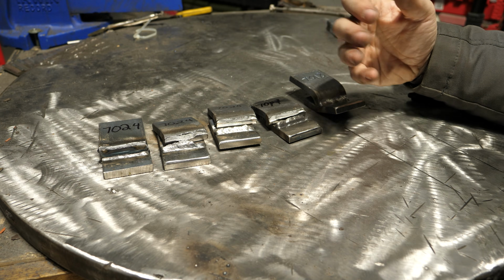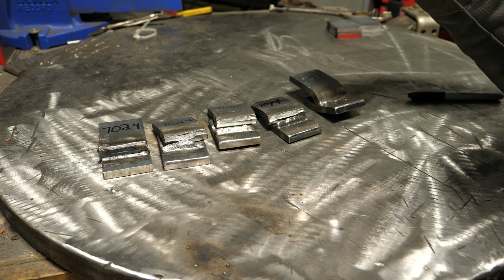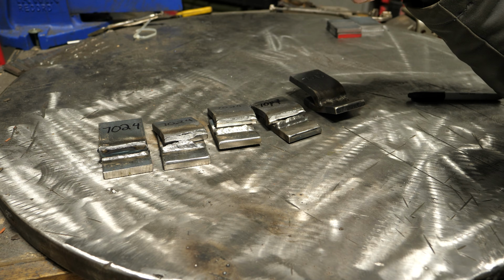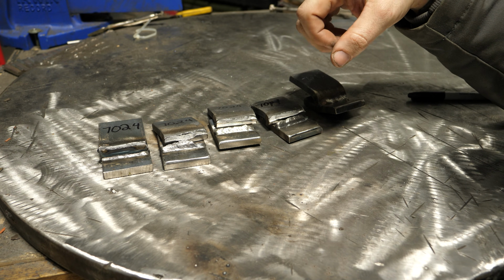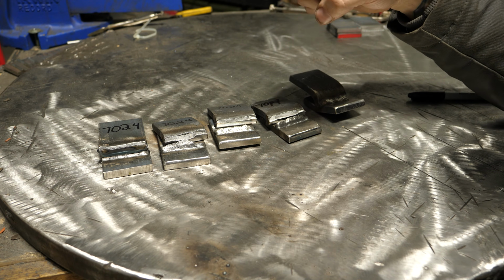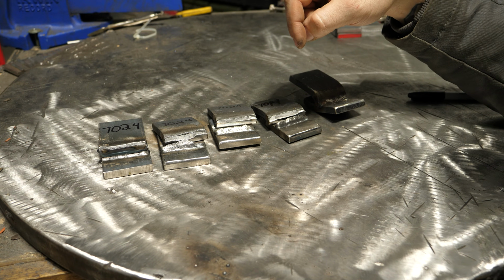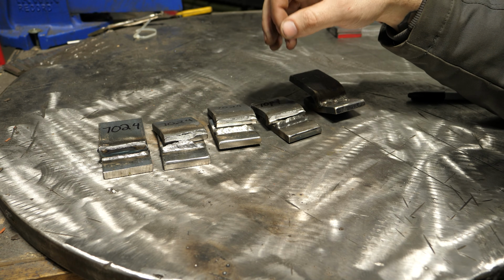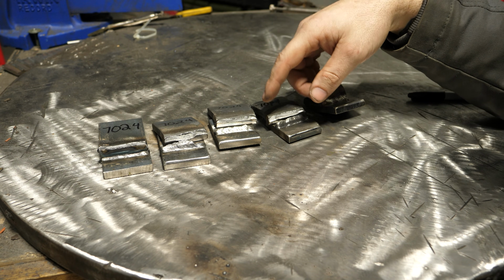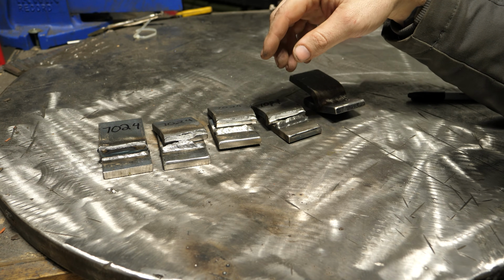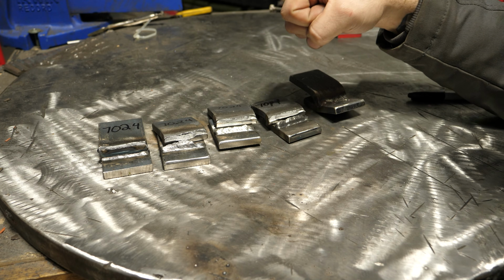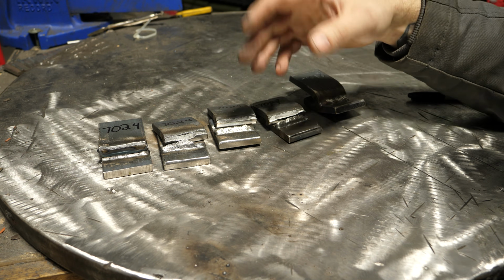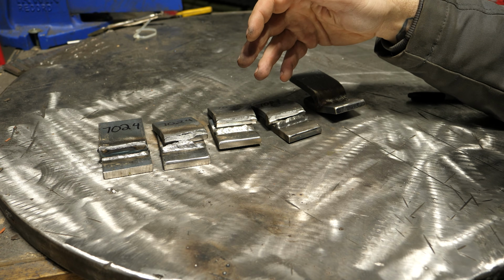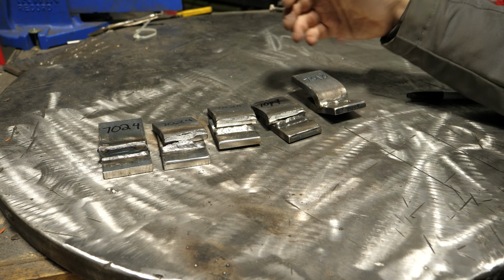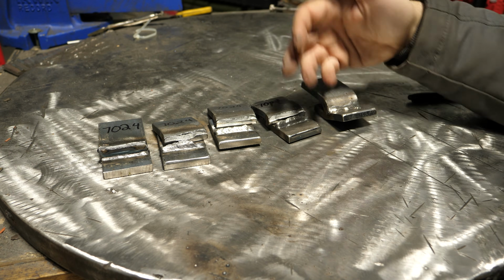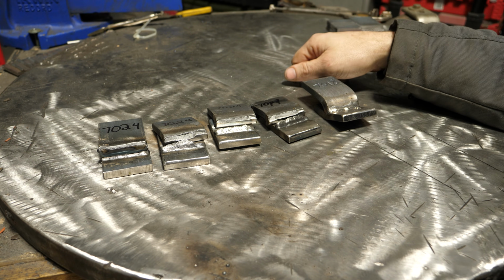From my perspective, I would say the 7024 under max load seems to be more brittle. And we saw that where it just catastrophically failed. And by the way, I can tell when I'm putting pressure on it in the shop press, it seems like it doesn't give a whole lot of warning and then it fails. It's not quite as bad as gasless flux core. That's probably the worst that I've experienced for pressure versus up until failure. But it definitely does not perform as good as 7018. And I hate to keep talking about 7018 and bringing this in, but the performance is not as good.